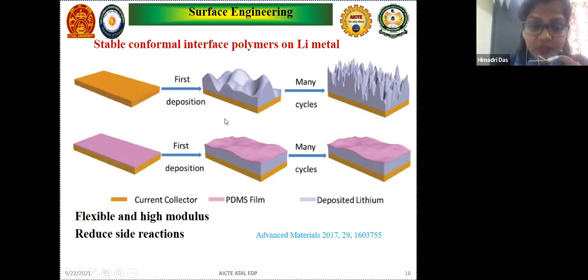So when we go for a coating of any polymer or any other material, like sputtering of gold or anything on this lithium surface, there will be a reduction of dendrite formation, and it can form a flexible and high modulus electrode. And the most important thing, the side reactions, as I mentioned in my first slide, many other side reactions happen, like people study with gas chromatography or HF production and all that. Those things will be reduced when we go for such approaches like coating or surface engineering of this electrode material.